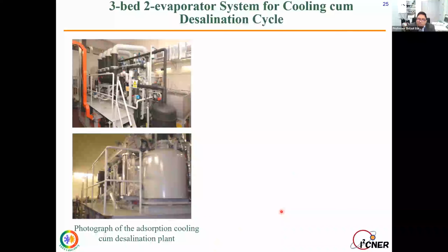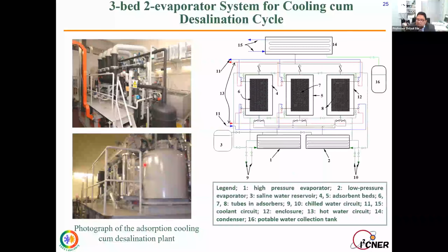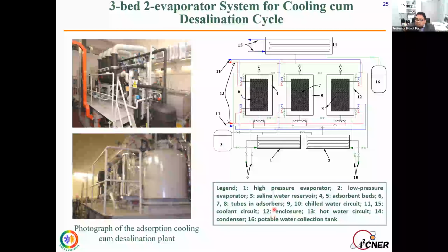And this is the experimental photograph of this cycle. Our low pressure evaporator is here, so we can get very high grade cooling. The high pressure evaporator is there, and we have 3 identical heat exchangers here, and our condenser is here, and 16 is our potable water tank, so that we can get cooling water as much as we want. Also, if we don't need any cooling energy, we can use this energy to cool down our bed more, so we can optimize our water production from the same cycle. It depends on our situation.